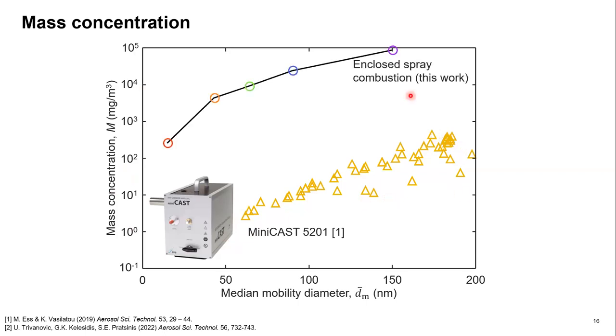When we compare this to enclosed spray combustion, we see that for all of the median mobility diameters, the enclosed spray combustion soot is three orders of magnitude greater than that of the minicast. And we attribute this first to the use of realistic fuels. So these liquid fuels have more energy density compared to the gaseous fuels that are used in the minicast and thus produce a lot more soot.